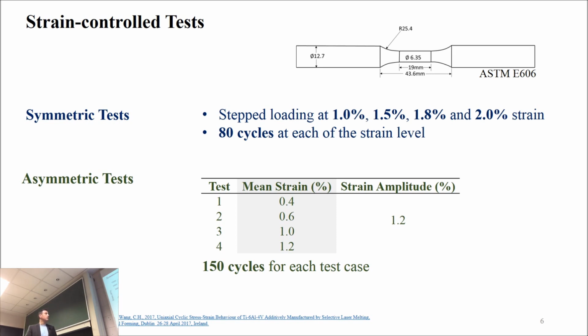In terms of the symmetric tests, again, as I mentioned, we're talking about the step test. So at each strain level, we complete 80 cycles, and then we move to the next level, and so on, until we get either a failure or we get the prescribed number of cycles, in this case 80 cycles. The left graph shows the first cycle out of this sequence for each of the 4 different strain ranges, and the right one shows the last cycle, which is the 80th cycle, both for the wrought metal and the SLM metal.